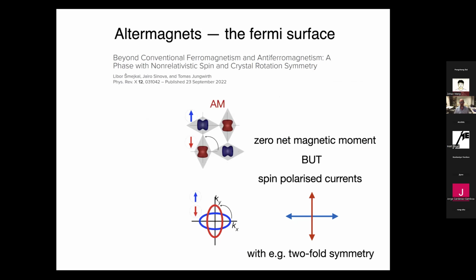Okay. So what is an immediate consequence of that, or at least hand-wavingly? It's interesting because in this altermagnet, I have a zero net magnetic moment, but I can have spin polarized currents. So the idea of that is as follows. If I have these two Fermi surfaces of the spin up and the spin down bands, if I apply an electrical field along x, the velocity in this x direction of the up spins and of the down spins is in general different. So if I apply this electrical field along x, the up and down spins will be accelerated at a different rate, and therefore I will get a longitudinally spin polarized current along the x-axis. If I apply the same field along the y-axis, I will get the same spin current, only of opposite sign.